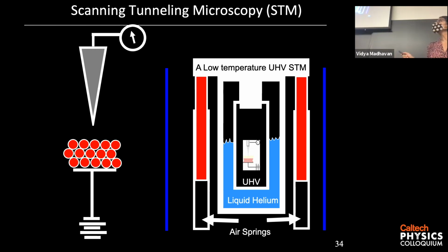The only problem is because the tip is so close to the sample, just a few angstroms, it means that any noise or vibrations can actually disturb the system quite a lot. So our experiments are always in the basement inside a soundproof room. And not only that, they're mounted on these vibration isolation legs and so on. So the experiments I'm going to describe today were done at very low temperatures, 300 millikelvin, not that low for the dilution fridge people, but still low temperatures. One of the reasons is that superconductivity happens at low temperatures, but also at low temperatures, you can get very high energy resolution.